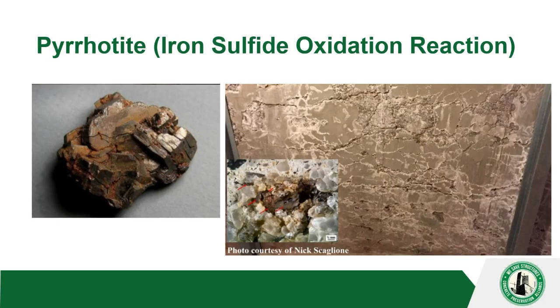Here's another one, pyrrhotite. And as you can see, it can be really severe. Pyrrhotite is an iron sulfide oxidation reaction. It reacts with water and oxygen, and it creates an acid, and that acid will attack the reinforcing steel and the concrete along these cracks.